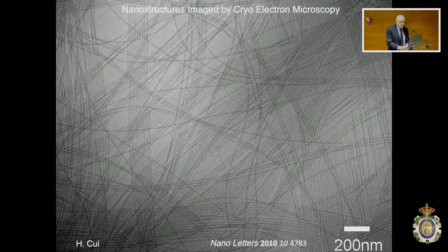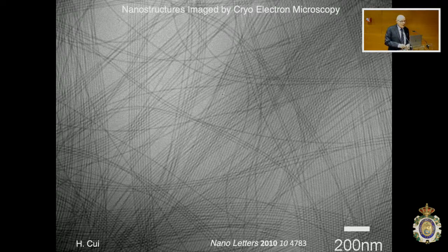You see them here by cryo-electron microscopy. They are extremely long filaments, microns in length, sometimes macroscopic in length, but the diameters are only about 10 nanometers. So the aspect ratio is enormous. It's comparable to carbon nanotubes. Okay, so they're really interesting materials. They present signals, and if they are made from these monomers, they're completely biodegradable. They would biodegrade very fast, either in vivo or even ex vivo, because they are made of natural structural units, amino acids, lipids. We use sugar moieties to construct them. We use nucleic acids and various things of that sort.